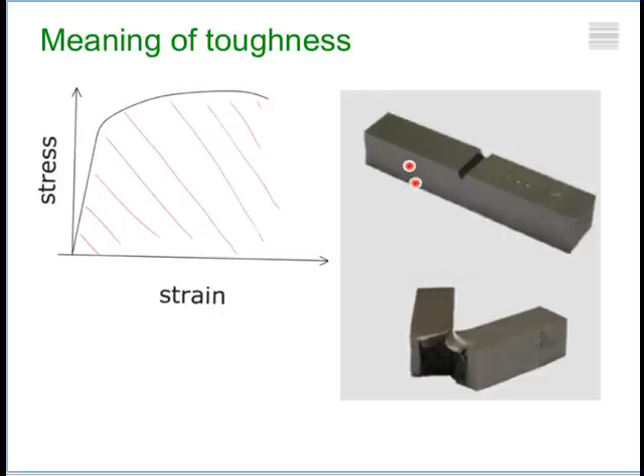So the standard way of measuring the toughness is to make a Charpy specimen which has a V-notch on it. And when you break it, you measure the amount of energy that's absorbed. And generally speaking, you do this as a function of temperature, because a steel normally becomes more brittle as you go down in temperature. So that is the meaning of toughness.